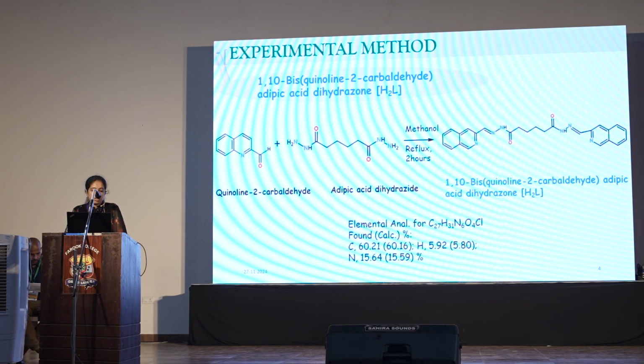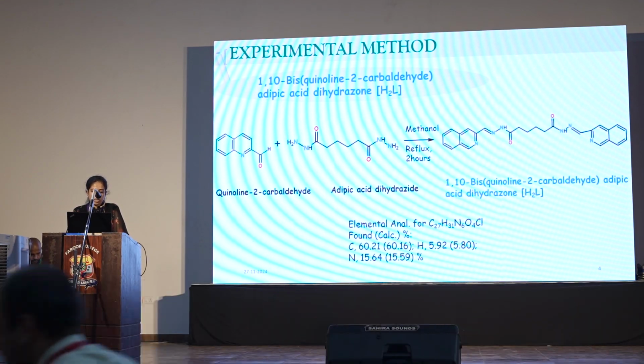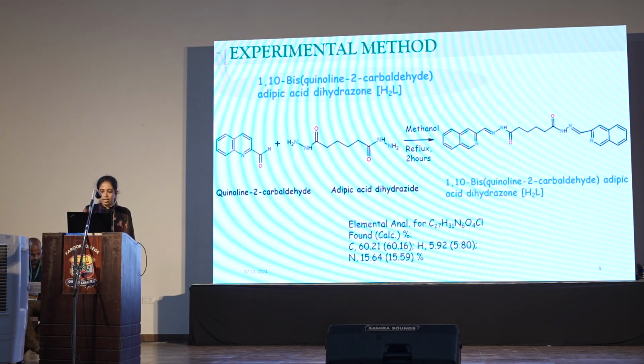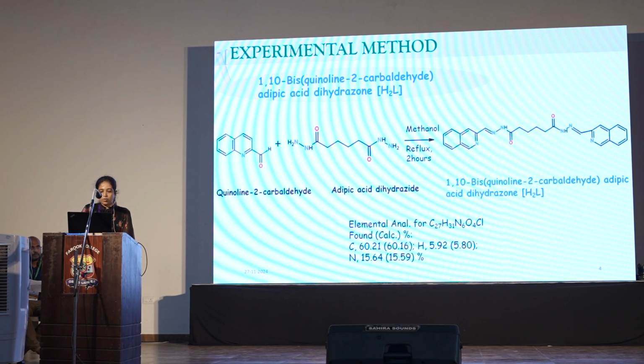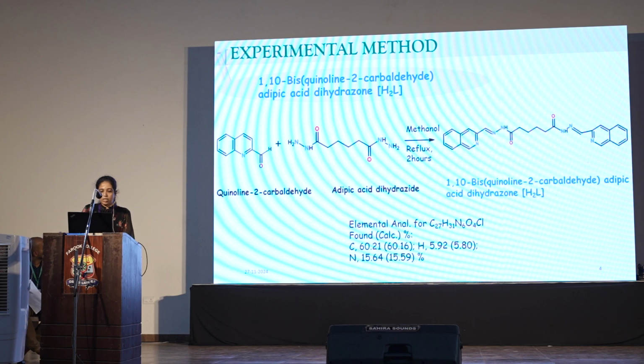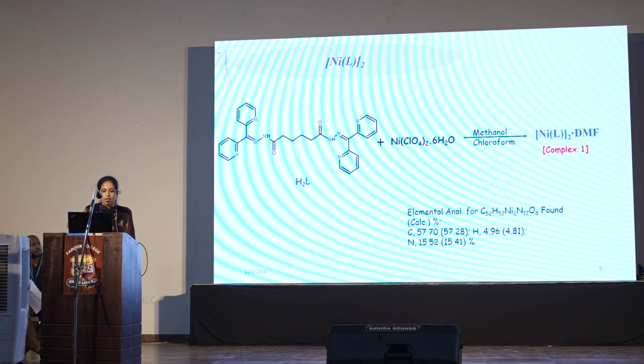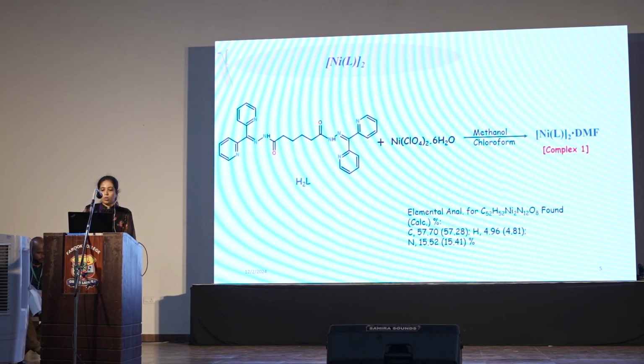Moving on to the experimental method, here we have synthesized the ligand 1,10-Bis(quinoline-2-carbaldehyde) adipic acid dihydrazone by refluxing quinoline-2-carbaldehyde and adipic acid dihydrazide for 2 hours. The structure of the ligand was primarily established by elemental analysis. Subsequently, the ligand was refluxed with nickel perchlorate salt in a methanol-chloroform solvent mixture to form complex 1, which is NiL2.